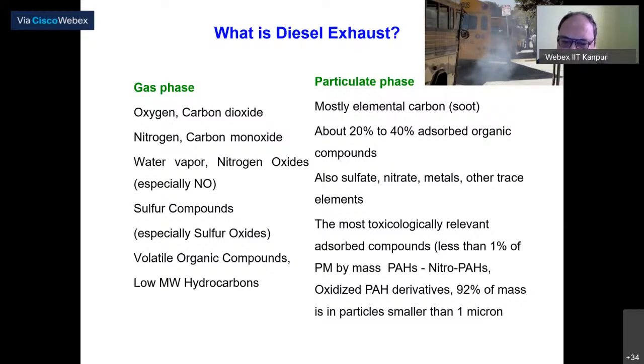If you want to understand simply what exactly it consists of, there are a bunch of gas species which come out from diesel exhaust. These, of course, are oxygen in small amount, carbon dioxide, carbon monoxide, oxides of nitrogen, NO, NO2, oxides of sulfur, volatile organic compounds, and some low molecular weight hydrocarbons, which are in gas phase because of the high temperature at which they are emitted. Now, in terms of particulate phase, we definitely have the elemental core of the soot.